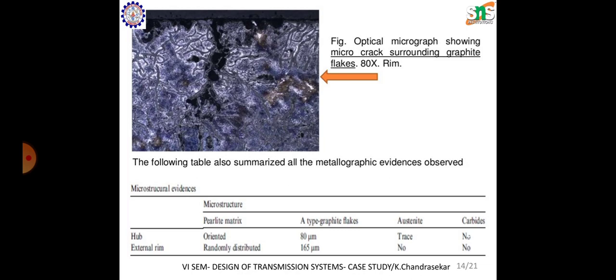In the microstructure, the pearlite matrix in the hub is very well oriented, while in the external rim it is randomly distributed. In the hub, A-type graphite flakes occur at 80 micrometers, and in the external rim 165 micrometers. Some traces of austenite are found in the hub, while in the external rim no austenite is found, and in both hub and rim there are no carbides.